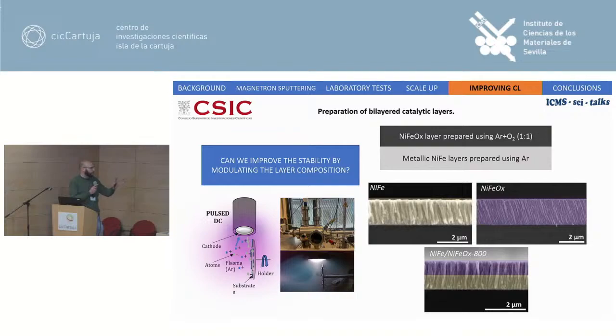Here you can see 3 examples of the catalytic coatings that we prepared. If we want to prepare a metallic catalytic layer, we use argon as a sputtering gas to obtain metallic nickel iron, and we try to oxidize our catalyst under vacuum condition to promote the formation of a more stable layer. So we prepared metallic nickel iron, oxidized nickel iron, and we also prepared the bilayer one to compare the behavior. In the paper, there is much more information about how we developed this bilayer catalyst, how we tested it to prove that effectively the most active and also the most stable catalytic layer is the one that combines both layers, the metallic and the oxide one.